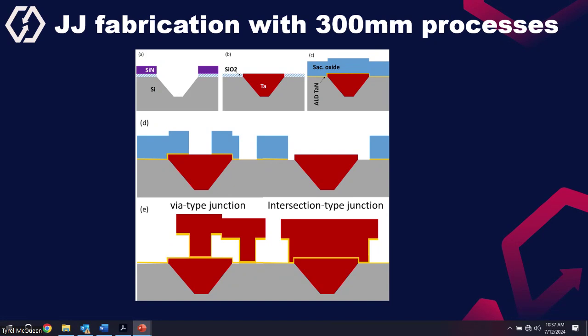So here we create a dielectric stack. In this dielectric stack, this is silicon nitride, silicon dioxide, and then we create a trench in this. And then we create a trench in silicon using the wet etch processes. This is known as the Damascene approach, which is well known in the semiconductor industry, but it is not used in quantum.